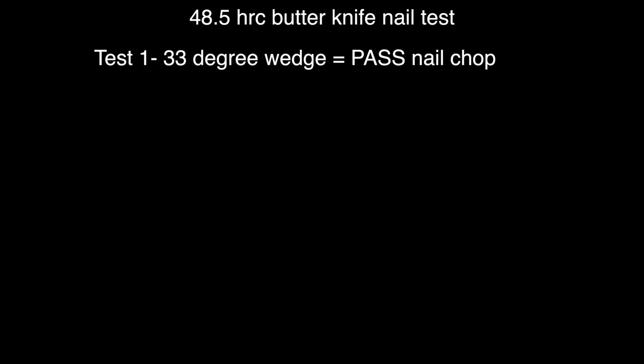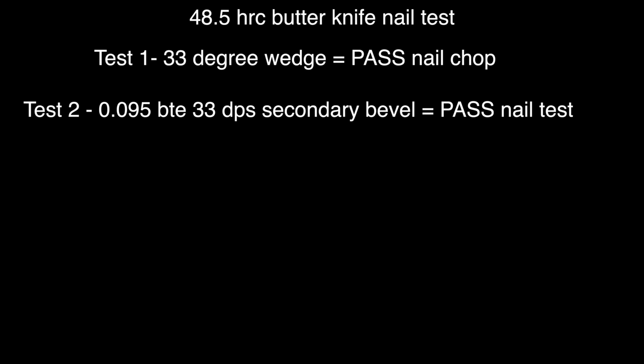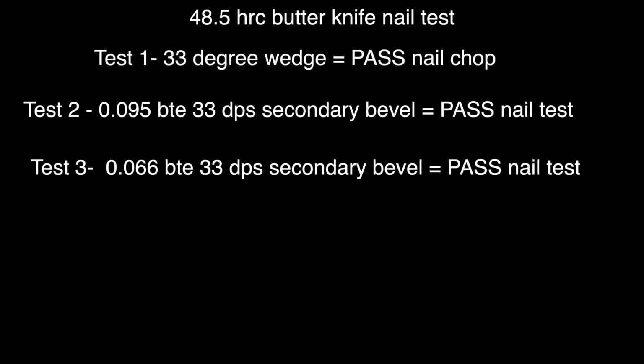So here's our test results for our 48.5 HRC butter knife. Test 1, with a 33 degree wedge shape, we were able to chop a nail with no damage. Test 2, with 95 thousandths behind the edge and 33 degrees per side secondary bevel, we again pass the nail test with no damage. Test 3, with our 66 thousandths behind the edge, our 33 degree secondary bevel, again, we pass the nail test.